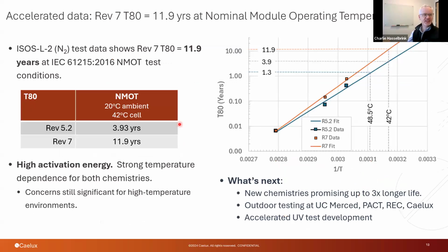Now, one test that we do find does seem to be reasonably predictive. The only remaining issue, of course, is what is the right temperature to use, and that can be complicated. Is the Arrhenius approach we use ISOS-L2 currently. We're working towards ISOS-L3 with some cycling going on in there.